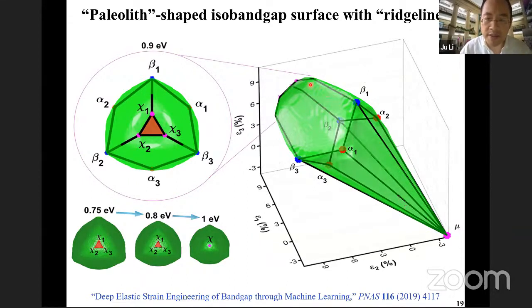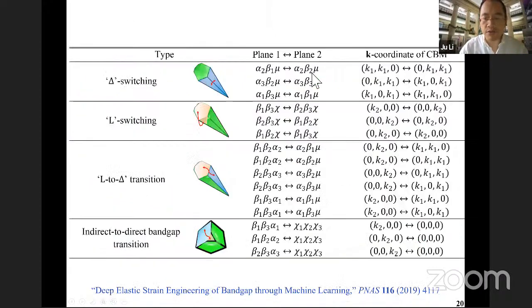And so we see it is piecewise continuous, but then you have these ridges, and 3 ridge lines come to a cusp point. And this is because band gap is the difference of 2 quantities, the conduction band minimum and the valence band maximum, and for each of the CBM, you can have a crossover. So we can use machine learning to classify the symmetries of these symmetry switchings in the iso band gap surface.